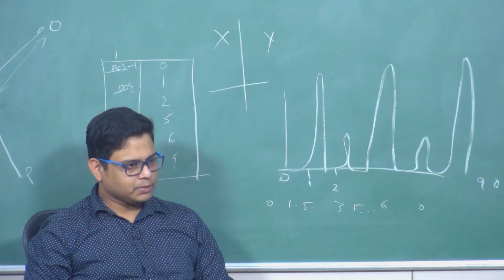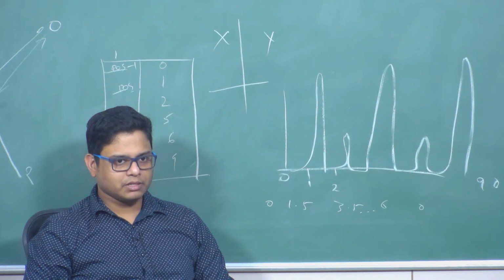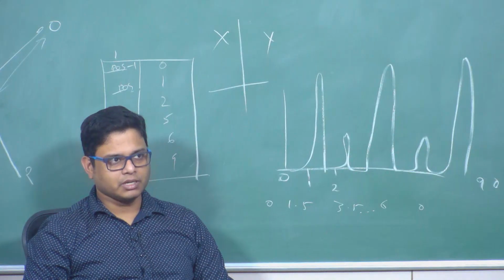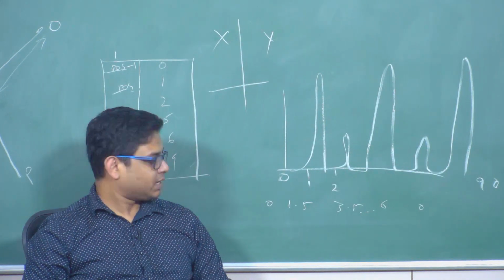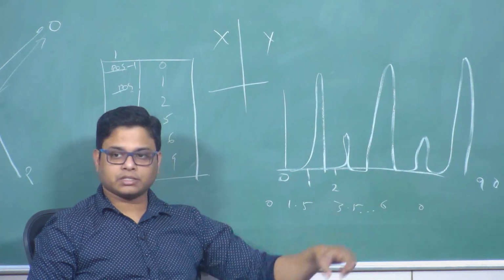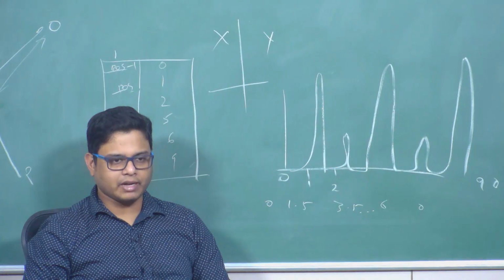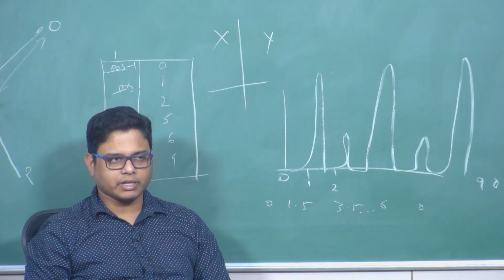Although it looks very simple, although X-rays have been discovered for 100 years, I think 1895 or something like this, more than 100 years actually, very interesting. But still nowadays, there is no unique method that can map from XRD to crystal structure efficiently. There is none. There are some methods like Rietveld refinement and so on, but they are very inefficient. There are a lot of things you have to do manually.